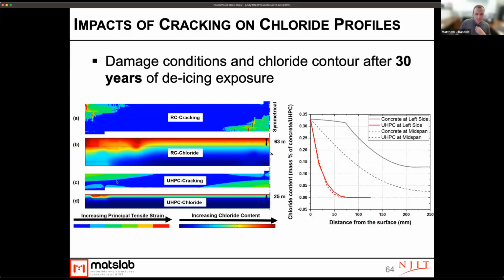The other thing we can look at in figures B and D are the chloride levels that we see in the different systems. And so what you see after 30 years of exposure is significantly higher chlorides in the reinforced concrete member as compared to the UHPC, despite having additionally the smaller depth. And so much like we looked at chloride at various depths from our experimental specimens about 20 minutes ago, we can simulate the same sorts of things in a representative bridge deck and look at, basically, how much chloride might we expect an inch down into a member in one of these UHPC systems versus a concrete after 30 years of exposure.